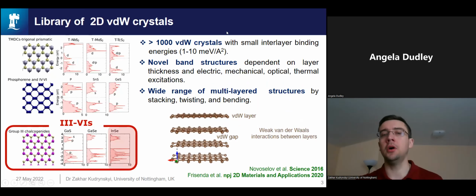So there is a wide range of van der Waals crystals. More than 1,000 of them are known so far. And what is common for all of them is that they consist of separate layers weakly bound together by van der Waals forces, which make these systems naturally favorable for miniaturization to create truly 2D crystals. Separate layers with the thickness down to 1 atom can be isolated, still preserving very good crystal structure. And our attention is attracted to this particular group of crystals called metal chalcogenides, with a specific focus on this particular one, indium selenide, which is a relatively new addition to the library of 2D materials.